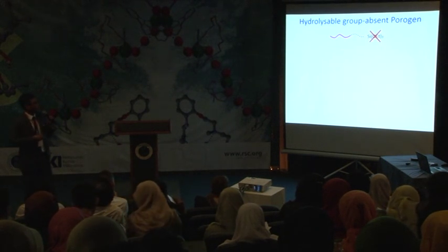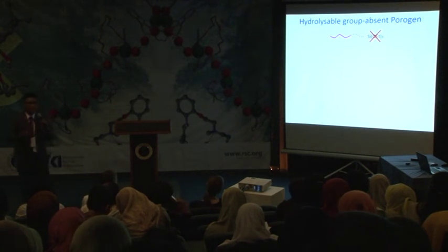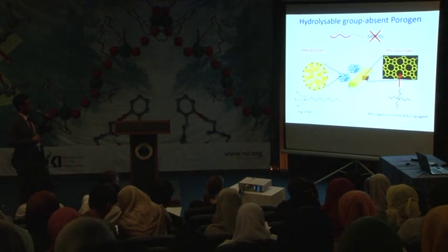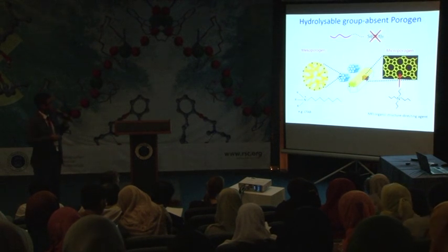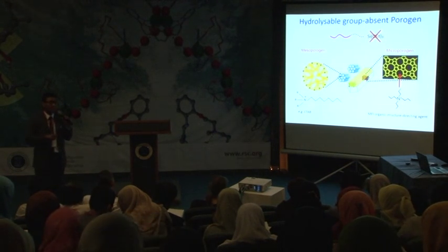Yes, next is what me and my students tried: to incorporate just the surfactants. Making this modified surfactant is quite tricky, because we need to synthesize and modify it in the laboratory first, because there are no commercially available modified surfactants for sale. So we try to avoid this if possible. But when we implement, like I said before, the normal surfactant like CTAB, it will form such a physical mixture. This is what we avoid.